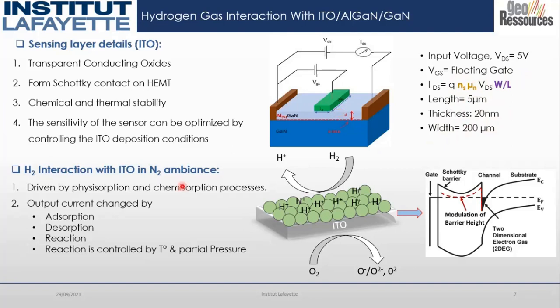So how does hydrogen interact with this ITO layer? The sensing mechanism of hydrogen on ITO is driven by physisorption and chemisorption processes. The output current is changed by the adsorption, desorption and reaction. This reaction is controlled by the temperature and partial pressure. When hydrogen interacts with the ITO layer, the barrier height is decreased, so more electrons can flow. So an increment of current is measured at the output of our device.